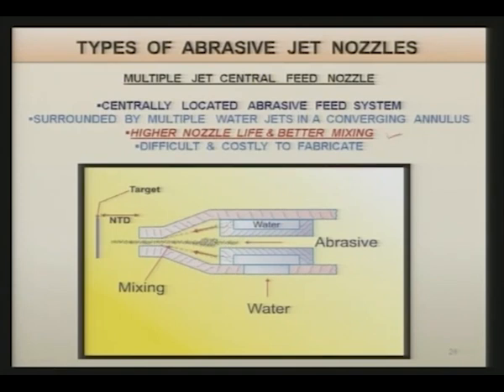If you see this figure, here water is in contact with the sides or inner surface of the nozzle; the abrasive particles are not directly in contact with the inner surface of the nozzle. That is why the life of the nozzle is higher compared to other types of nozzles, and mixing is also inside the nozzle, giving better mixing compared to other nozzles. As you can see here, the nozzle tip distance is shown, and water is coming from the annular side, from all around, and that is why it is known as the multiple jet central feed nozzle.